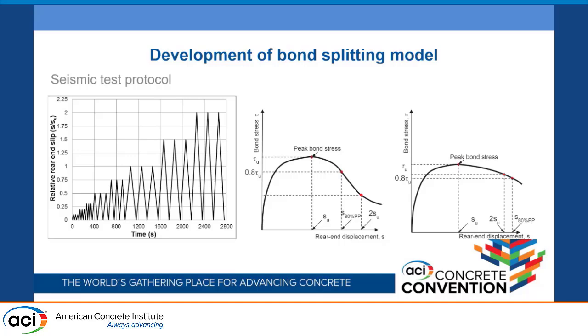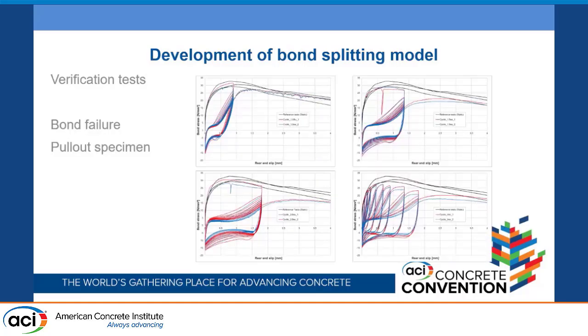So we increase the displacements, the rear end displacement or rear end slip of the rebars, with initially 0.1 times SU, then 0.2 times SU, 0.3 times SU, 0.5, 0.75, and so on. And if we do this, then we can get the full load-displacement curve. Also, long back, Professor Eligehausen gave the testing protocol for cast-in reinforcing bars, where we provide typically 10 cycles at constant slip, and then we do the residual pullout. So we wanted to compare how our protocol works with the protocol which was given by him for cast-in rebars.